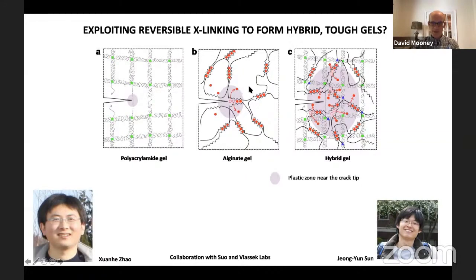Now, in contrast, with something like an alginate that is reversibly cross-linked and can dissipate energy because it's viscoelastic, some of that energy would be taken up by decross-linking. The gels, though, because they're formed from relatively weak bonds, don't absorb a lot of energy. But what they proposed is if they combined a covalent network that could transfer energy over significant distances with this ionically cross-linked network that could dissipate the energy, this would create a large zone that would be absorbing energy, dissipating energy, and really toughening the material.